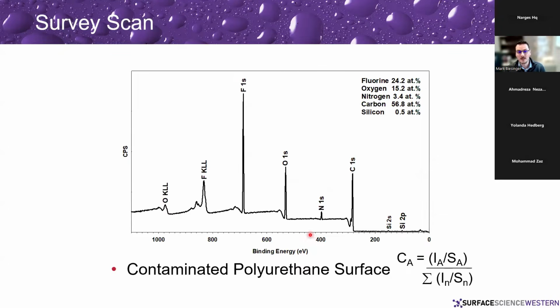Sometimes you'll see other peaks as well. So for example, we have a fluorine peak. We see the 1s orbital, but we also see structure from the fluorine Auger signal in here. Something like silicon, we've got 2 peaks that show up, silicon 2p and silicon 2s. And you can use what they call relative sensitivity factors in conjunction with areas under these curves to figure out how much of each element you have present.